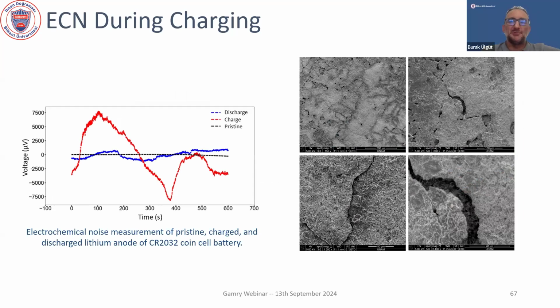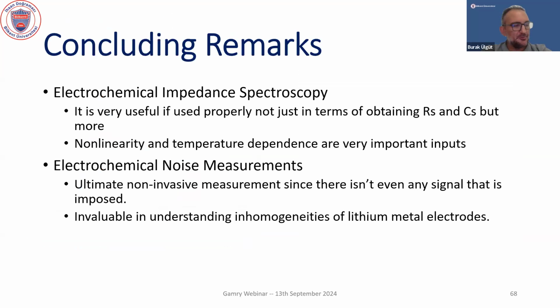This is very hard to do reproducibly because we don't have a good set of batteries and conditions that reproducibly plates. And we typically want to measure at least 8 cells before we are sure that this is happening. So we think we find at least, well, we have some more prospects that we are working on right now. And once we can find a good reproducible way to plate lithium in commercial batteries that we can reproducibly measure, we will come up with a way of identifying lithium plating via electrochemical noise on the voltage. Okay, I'm not going to go on to concluding remarks since I'm already 6 minutes over time.